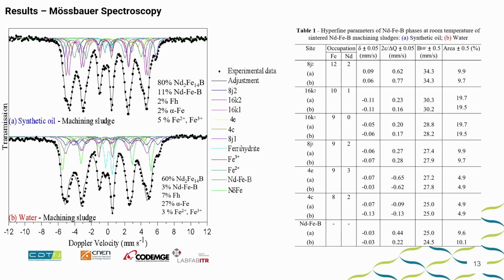When you fit here, we can find this phase with the 2-14-1 phase of neodymium iron boron, and the other with distorted structure, and the ferrite, the alpha iron, and the other cations. And if you cut the sintered permanent magnet, there is a significant reduction of this important phase of neodymium iron boron, and the other parameters are almost the same, but here we do not see a very high increase of the alpha iron phase in this spectrum.